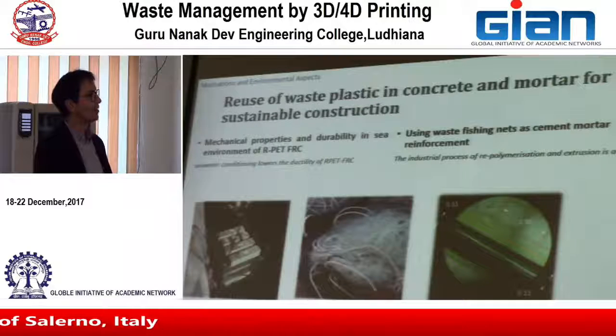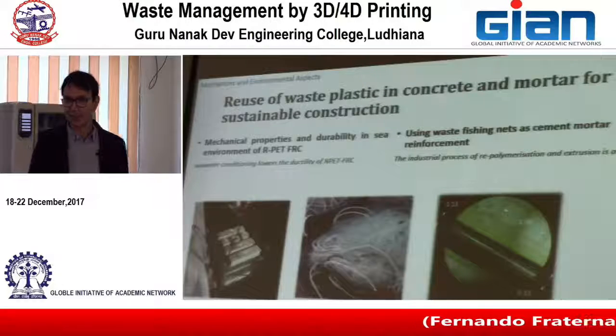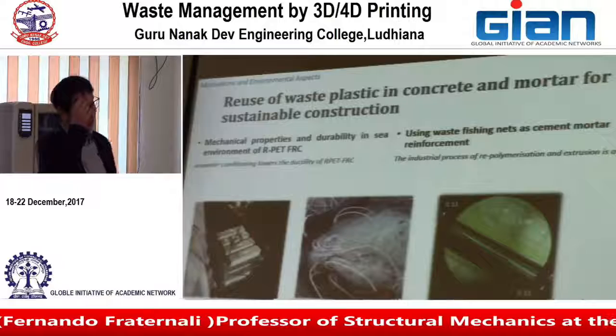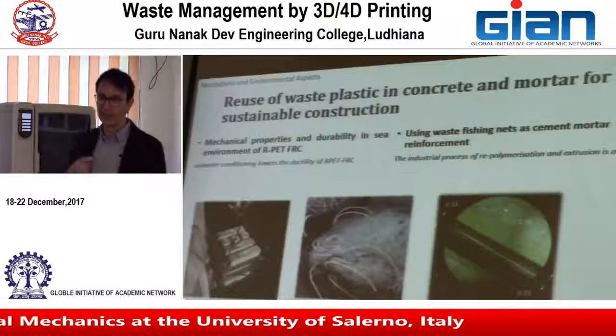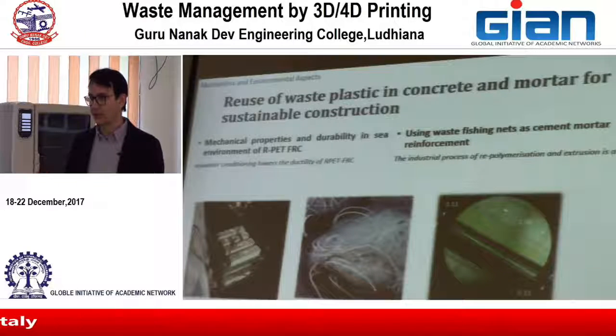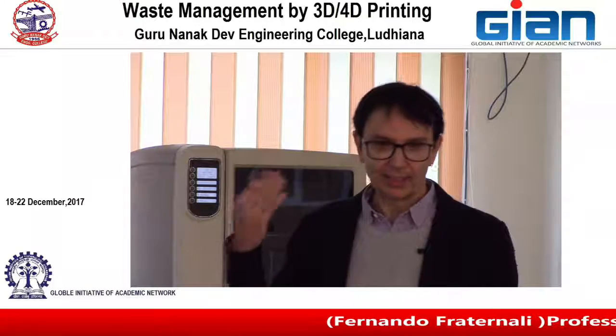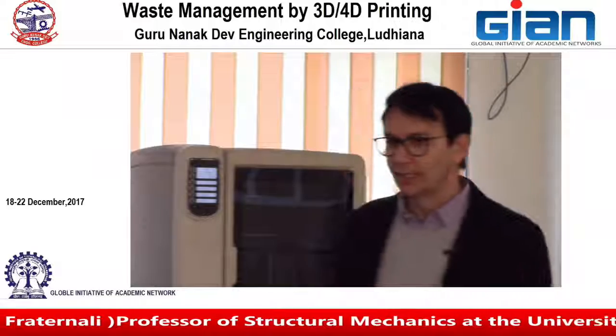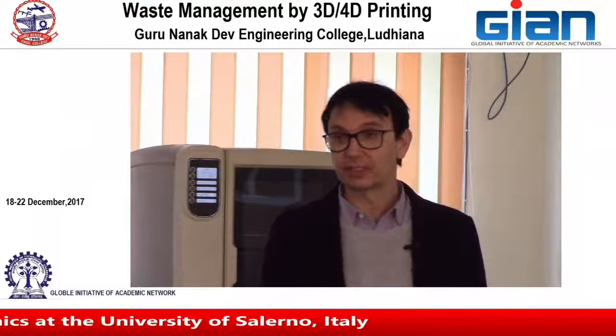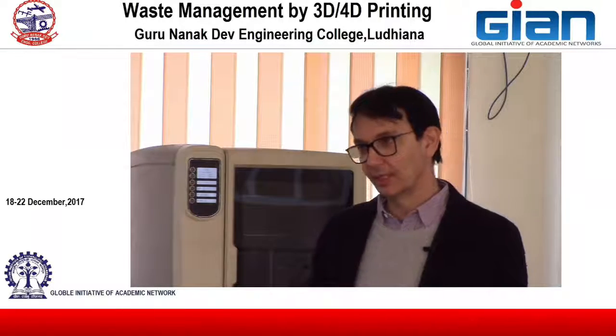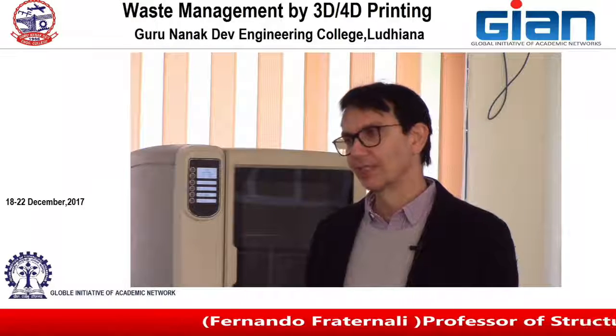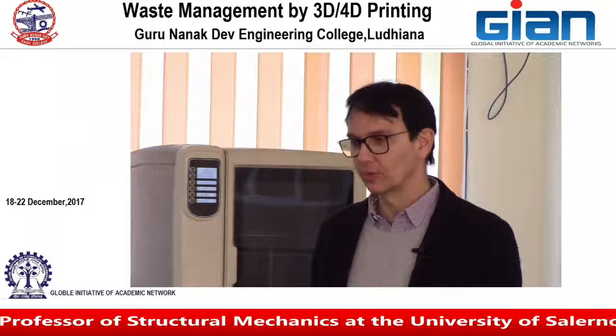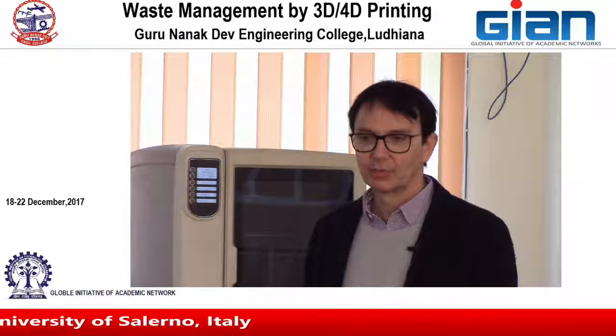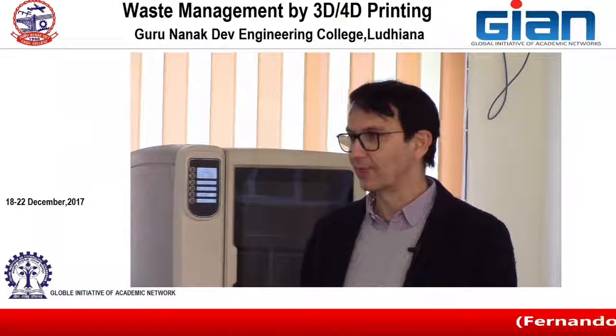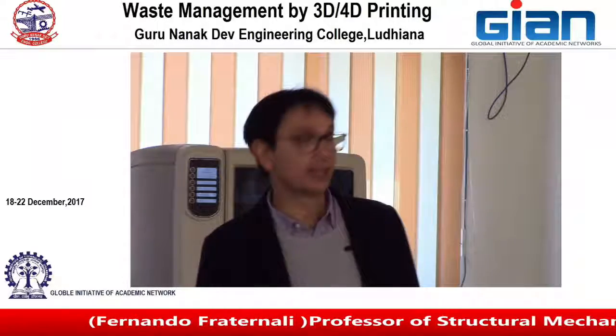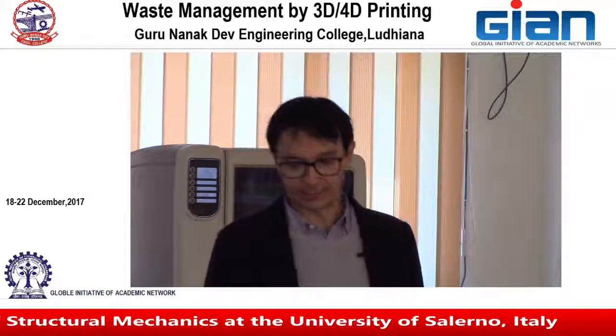We also carried out durability studies in this case. I didn't show before, but for the R-PET specimens, we complemented the study that we have seen before for the concrete reinforcement with the R-PET fibers. We extended the study that I have presented before by immersing some specimens in water for 1 year and measuring the decrease in mechanical properties after 1 year. And we observed good durability results of the fibers, which essentially derived from the fact that the fibers are protected by concrete in the aggressive environment. And so they preserve their properties.